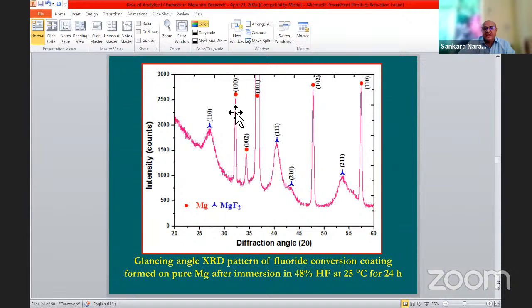The red spots are magnesium peaks. You can see how high the intensity of the magnesium peaks is. That clearly shows that the thickness of the film is very, very thin, even in glancing angle XRD. In glancing angle, the angle of incidence is less than 5 or 10 degrees, so that is how you have to take it. So we could identify the formation of magnesium fluoride using glancing angle XRD.